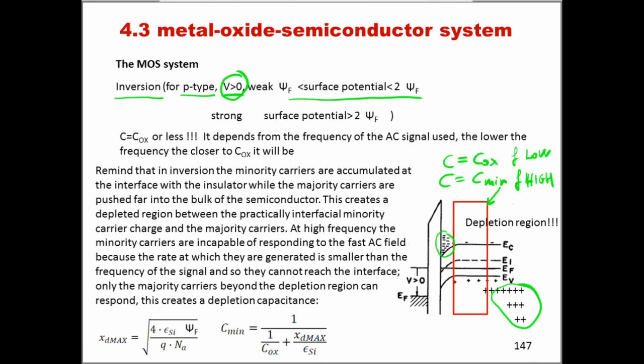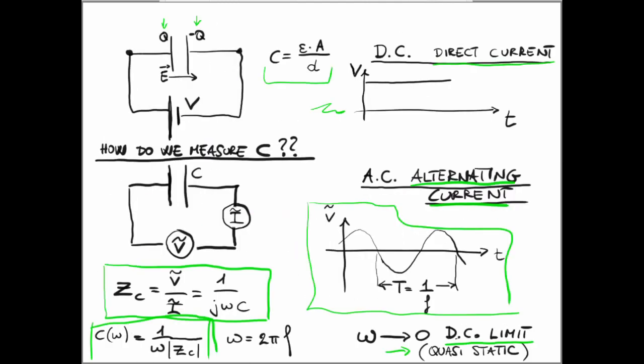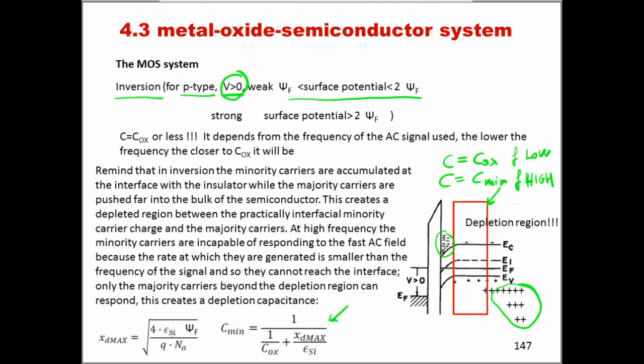These results are summarized in this slide here. In accumulation, the capacitance is equal to Cox, the capacitance of just the oxide, for every frequency we use. In depletion, the capacitance is given by the combination of the capacitance of the oxide and the capacitance of the depletion layer, for all frequencies again. In inversion, though, the capacitance of the device will be just the capacitance of the insulator if we are at low frequencies, or it will be equal to a minimum capacitance when we are at high frequencies. And this minimum capacitance is calculated in the way that I've indicated down here. Because we have a depletion layer, the depletion width can be estimated in this way, and so the minimum capacitance can be calculated in this way.